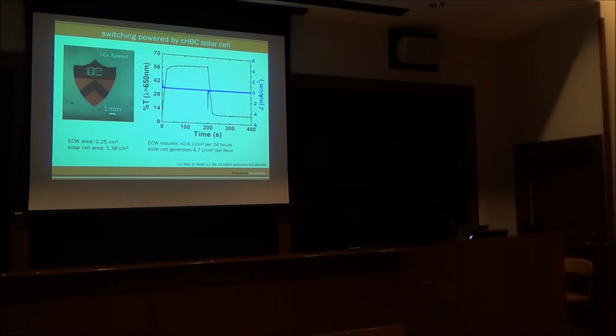You might ask, well, do you have enough power to regulate this? And the answer is yes. So it turns out that with our solar cell, with the efficiency that I was just telling you, if it absorbs light and generates power in 6 minutes, that amount of energy is enough to power your electrochromic window over a 24-hour period. So what this is saying is, if we have a small capacitor or a small battery, what we can do is store the rest of the power and operate the electrochromic window in the dark on a cloudy day when it's raining.